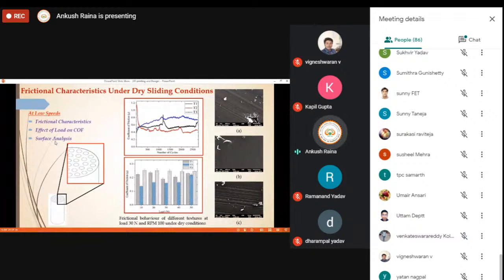So this figure is regarding the frictional characteristics. It gives the variation of coefficient of friction with the number of cycles at 30 Newton load and 100 RPM under dry conditions. For texture T1, the coefficient of friction increases linearly up to 1100 cycles. So for texture 2, the coefficient of friction is high at the start.